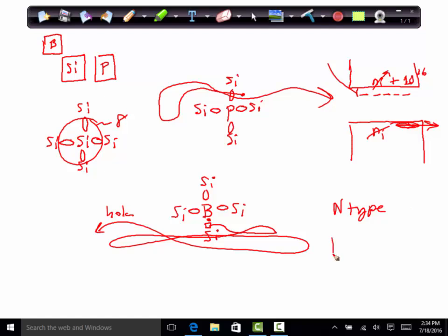And then P-type, the boron is the most common, but aluminum and gallium are also sometimes used, especially in photovoltaic devices. And again, the N and the P refer to the charge of the charge carrier. And it does get a little confusing, I understand, when you say P-type, but then the element symbol P stands for phosphorus, which is actually an N-type dopant, so don't mess that up.